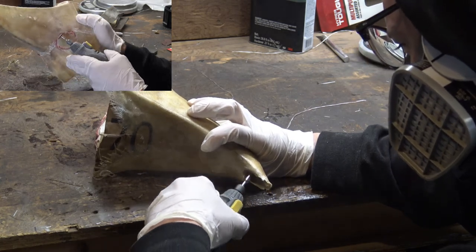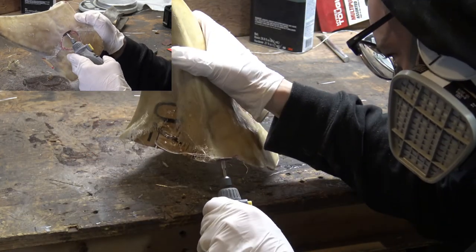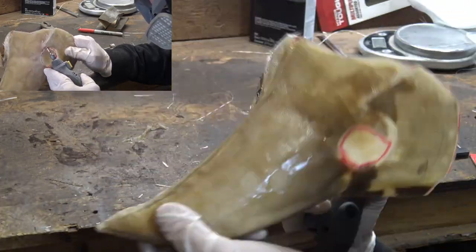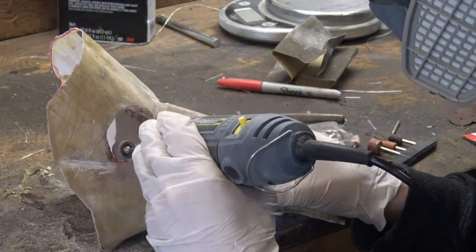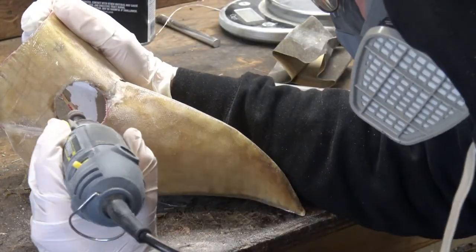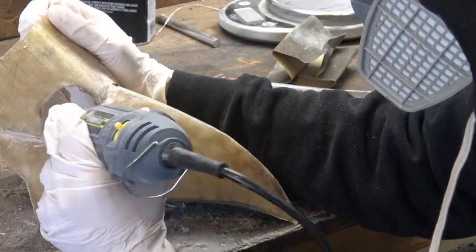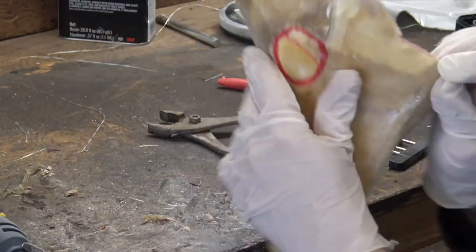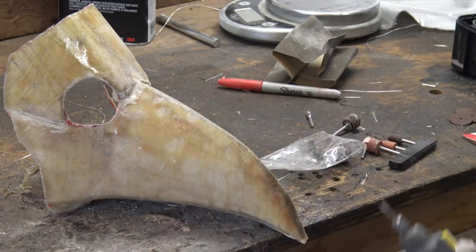Now, this type of drape molding worked really well for the initial shell, but one of the problems was obviously on the very bottom. It was not fully formed around the bottom of the cardboard, and because of that there were a lot more air pockets that had to be worked out. Whenever you're working out air pockets, you go slow and gentle to the touch, because you can just blow through, especially when it's only three layers thick like this. And I ended up just removing a whole small section on the bottom because of it.